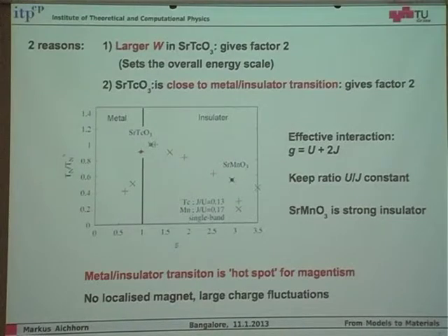And this information you might even use for what we call material design. So if you look for magnets who have strong, not strong magnetism, high Néel temperatures, let's call it this way, you look for something that's not on this side, which is a very strong antiferromagnet, but you look for something which is on the verge of being metallic. So that is what we call material design, that you look at the calculation, try to use this information to look for new properties of new materials.